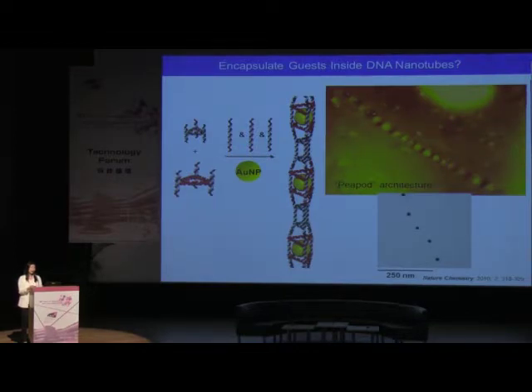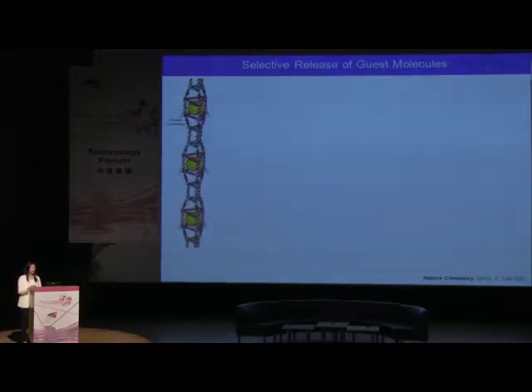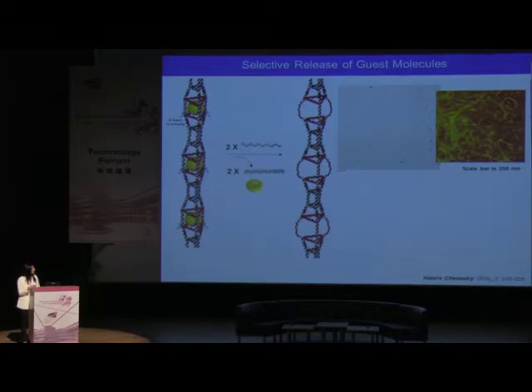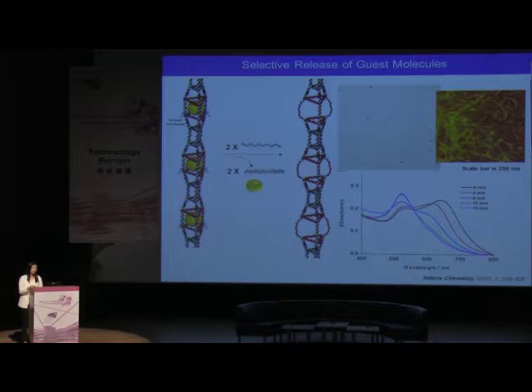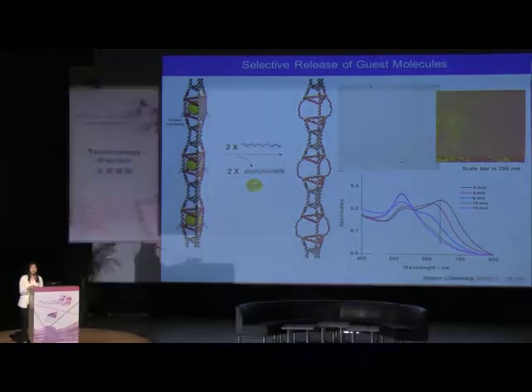So after we encapsulate the materials inside, how can we release them? In here, we just modify a little bit on the design to have the sticky end with the overhang DNA strand on two sides along the nanotube. And then we add the complementary eraser DNA strands. So what happened is that the closing strands are removed and form the double helix here. And at the end, the nanotube becomes partially single-stranded, and the capsules are open now. So the gold nanoparticles are completely released from the nanotube. And we also studied the kinetics, and that process is very fast, just finished within 15 minutes.